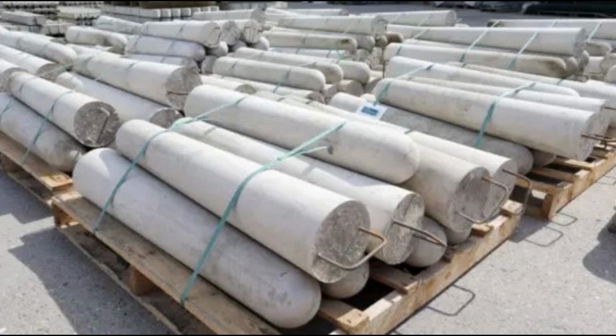The cement produced for making concrete accounts for about 8% of worldwide CO2 emissions per year, compared to, for example, global aviation at 1.9%. The two largest sources of CO2 are produced by the cement manufacturing process, arising from: 1. The decarbonation reaction of limestone in the cement kiln, at 950 degrees Celsius, and 2. From the combustion of fossil fuel to reach the sintering temperature, 1450 degrees Celsius, of cement clinker in the kiln.